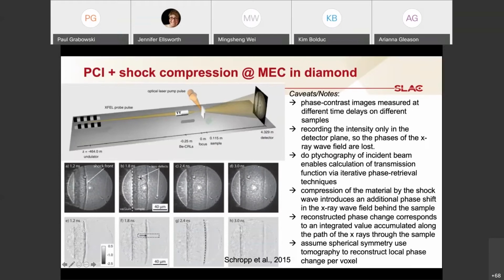But these features should be static. You can see we've got some third harmonic contamination here. That's this bright spot in the center of each of the images. And at different time slices, so these are each different samples now. Each time slice is a separate piece of diamond. This shock front moved forward, and then Andreas and others have looked at the density distribution across this front.